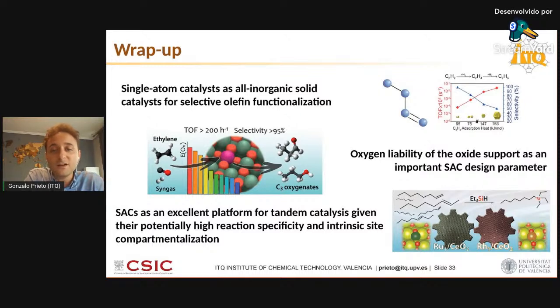First one where the oxygen lability on the oxide support, in this case cerium oxide, was a critical design parameter for a single atom catalyst, in this case to be unusually selective in the gas phase hydroformylation of ethylene. And in the second showcase, I was illustrating that single atom catalysts are also excellent platforms due to their higher reaction specificity and selectivity compared to catalysts where different types of metal sites are exposed on the surface, typically those based on nanoparticles. And so those features are particularly appealing in the area of tandem catalysis. And I hope I was able to illustrate that with this tandem olefin isomerization hydrosilylation process to produce terminal organosilanes with high regioselectivities, even from complex mixtures of internal and terminal starting olefins.